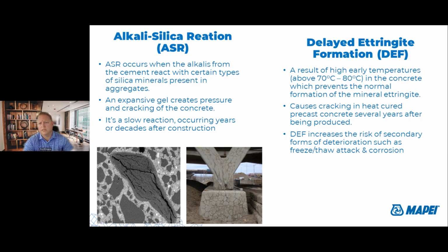Another one is delayed ettringite formation, or DEF. This is a result of high early temperatures in the concrete, which prevents the normal mineral formation of ettringite. This typically happens at precast yards if they're on a tight time schedule and trying to produce a lot of precast members. Sometimes those high early temperatures can cause problems. It increases the risk of secondary forms of deterioration like freeze-thaw and attack.